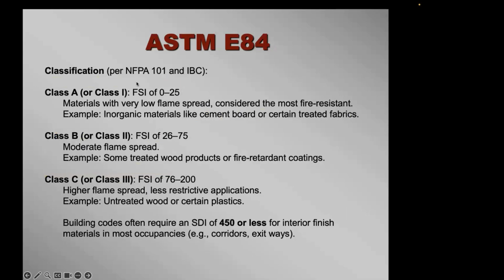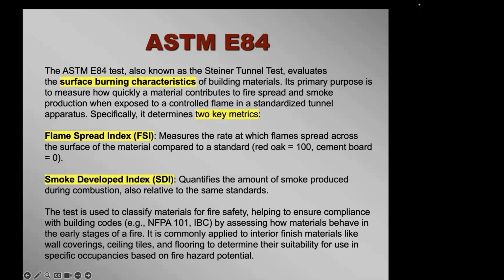So for your flame spread, your class A or class 1, this is where they say it's a fire rating. It's not a fire rating, it's a burn rating, and it is 0 to 25. Class B or class 2 is 26 to 75, and class C or class 3 is 76 to 200. For all classes, the smoke developed index is 450 or less. Let me just go back here. For flame spread, the barometer is red oak, which is 100, and then cement board is 0, because cement board doesn't burn.